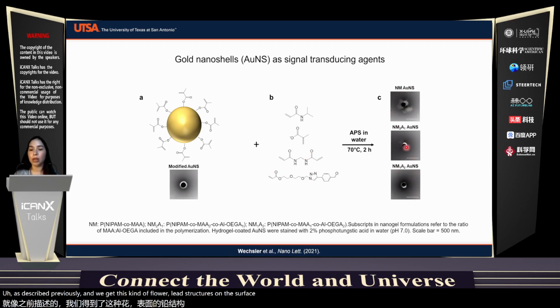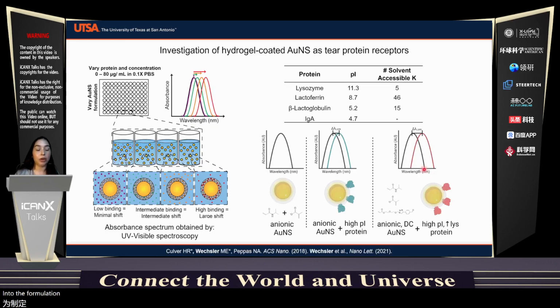And we're using the same formulations as described previously. Our control is NIPAM methacrylic acid, and then our NIPAM methacrylic acid co-AI-OEGA. Again, the subscripts refer to the ratio of methacrylic acid to AI-OEGA in the formulation. So again, we did this in phosphate buffered saline at pH 7.4. This time, this is a solution-based sensor. So we did this in a 384 well plate.